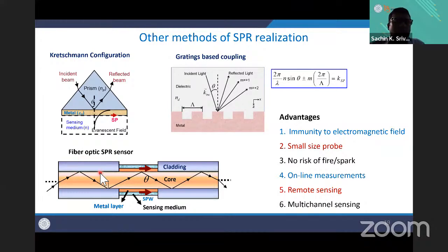There is one more beautiful physics. I will discuss that also, but remember this: you have a rough surface here, you made a rough surface like a grating, and then you can couple light to excite surface plasmons, and then you can simply replace the prism by using the core of an optical fiber, and it will do the same job like exciting surface plasmons in Kretschmann configuration. The advantage is that it becomes very small, and there is no risk of spark or fire, because this is purely light, and you can do online measurement. I am sitting in this room, I can do sensing throughout my city using optical fiber. So you can do remote sensing, you can make multiple channels, and you can do multiple channel sensing. Those are certain advantages of it.